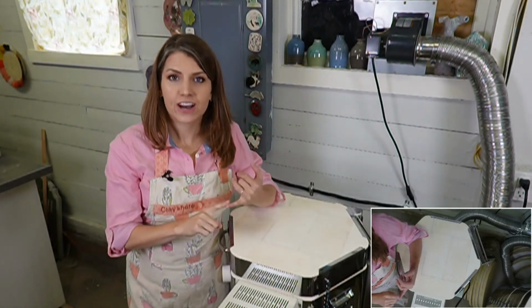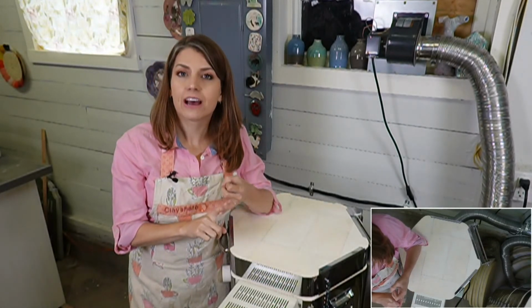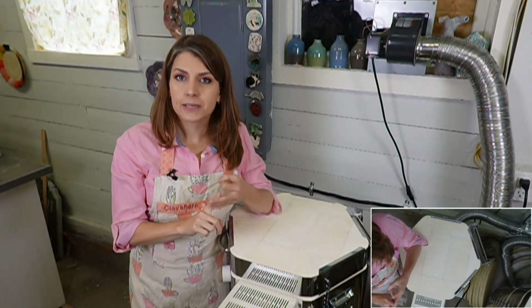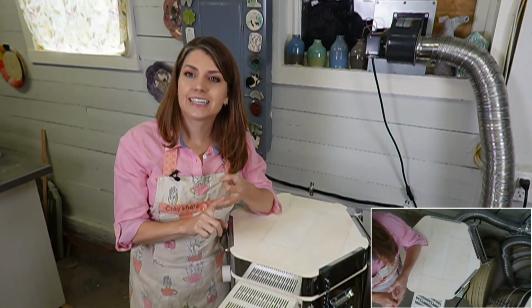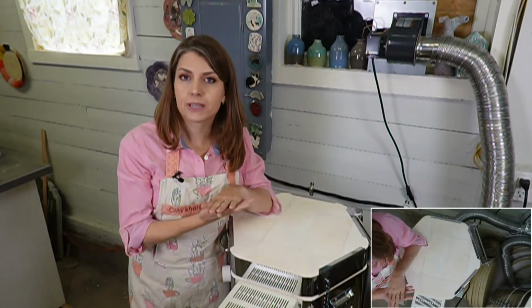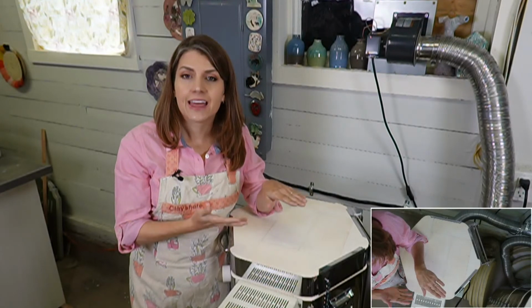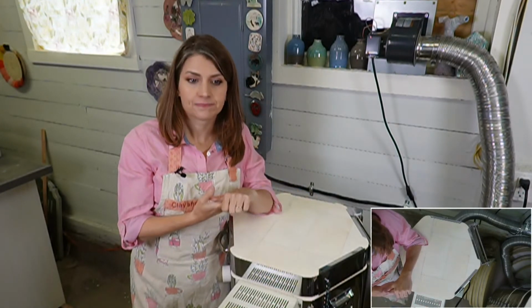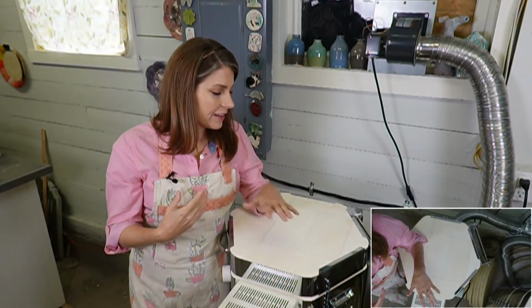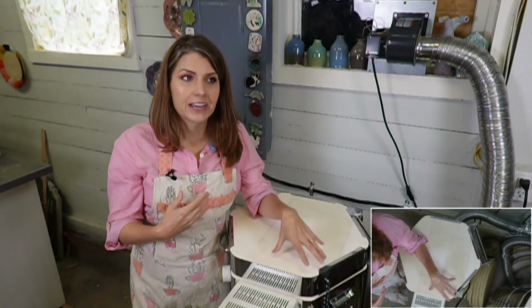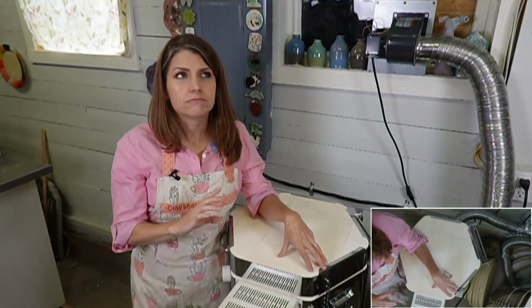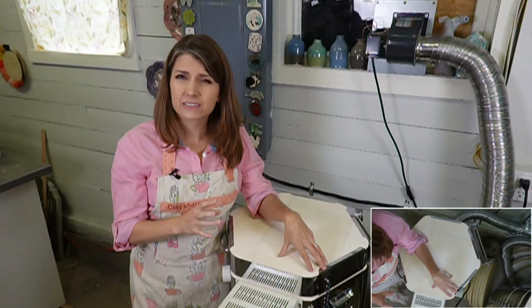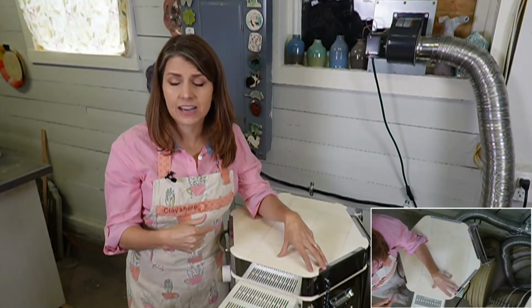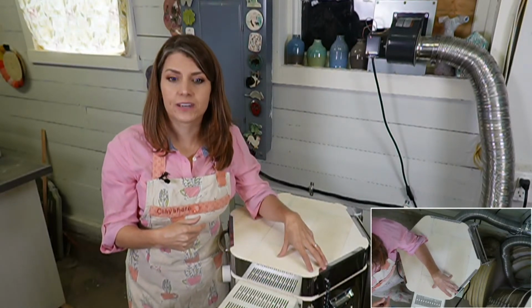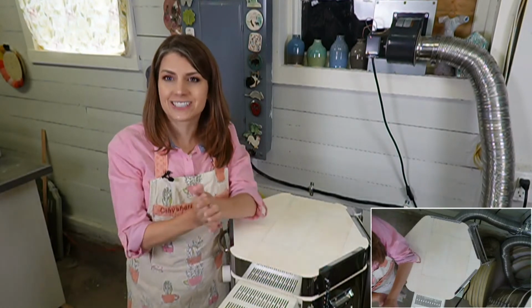So this was a cone 5 firing. I did an hour-and-a-half preheat. It was on medium speed, and at the end I did a 10-minute hold. So at the top temperature it held for 10 minutes, and then it shut itself off. Now it took 10 hours to fire. It finished up at about 5 o'clock, and now it's down to about 86, so we can open it up and check it out and see what's in it.